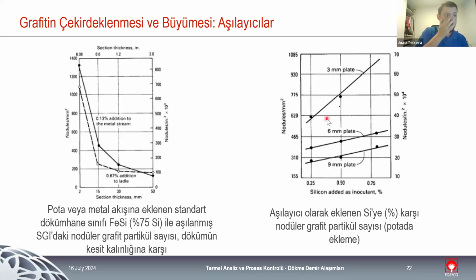And the same principle is used for the right picture. We can see that increasing the silicon content, we increase the nodule count. Silicon is really important as an element heading to the inoculation, because it's the element that increases the window between the stable and the metastable temperature. So we can see that even by adding a simple silicon alloy to the melt, we increase the nodule count in three different sections of the cast.